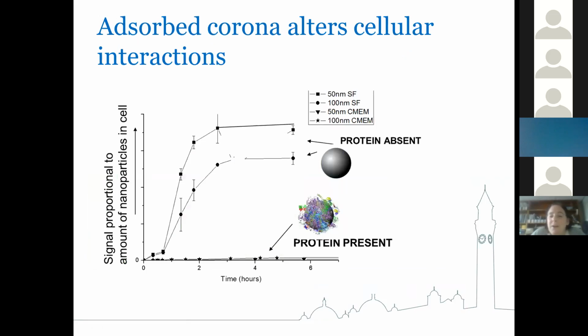This was quite an old study. This is about 10 years old now, but it's still nice to illustrate the point that in the absence of proteins, these were 50 or 100 nanometer polystyrene particles. And in the absence of proteins, an awful lot of particles were taken up by cells. These were A549 lung cells. And the reason that they were taken up is because the particles were so highly reactive that they basically just punched holes in the membrane, and then there was so much cell damage that they were easily able to go in. Whereas when there was this concept of the protein corona, when the particles were incubated in cell culture medium that contained serum proteins, so 10% fetal bovine serum, for example, which would be fairly standard in cell culture, then much, much less went in, but they went in through these very regulated cellular receptors.